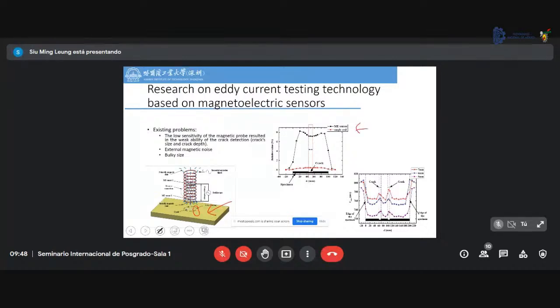The red one is the single coil, which is the commercial product, and you can find that the single coil can only detect the metal material, but it is very difficult to detect the crack. But if we use our ME sensor, we can find that even though we can detect the conductive material, we can also detect the crack here. And this is another kind of measurement result.